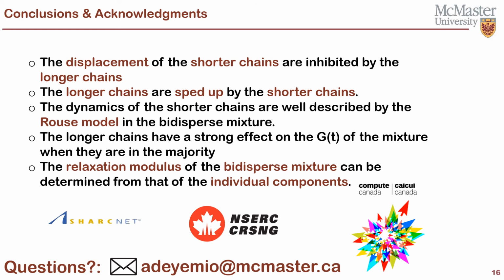We also showed that the longer chains have a strong effect on the relaxation modulus of the mixture, especially when they're in the majority, by amplifying the entanglement effects. When the shorter chains are in the majority, they dilute the effects of the entanglement. We also showed that the double reptation model reasonably predicts the relaxation modulus of the mixtures.